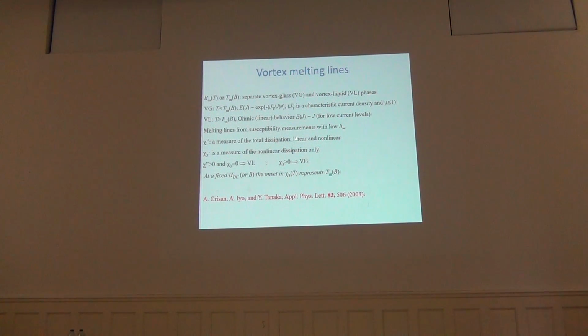So for low current levels there is a linear dependence of the dissipation on the current. On the other hand, when you do susceptibility measurements with very low AC fields, meaning a very low probing current, to stay at very low current densities, out-of-phase susceptibility is a measure of the total dissipation, which is linear and nonlinear, while the third harmonic is a measure of the nonlinear dissipation only. So if we have out-of-phase susceptibility larger than 0, but the third harmonic component is 0, then we are sure to be in a vortex liquid phase, while when we have an onset of the signal from the third harmonic, we know that we entered the vortex glass region.